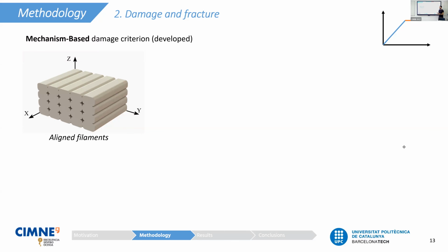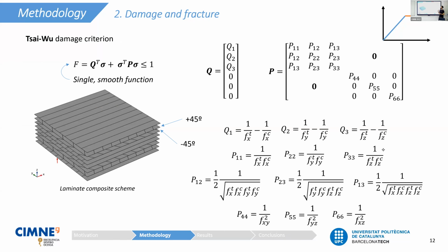However, the previous, let me go back 1 second. This Tsai-Wu damage criterion has one drawback, and that is it's a single smooth function, meaning it is just one scalar, and with just one scalar it is impossible to fully characterize all the different failure modes that are present in such a complex system. Because in the end, the different printing patterns present in a FFF component have more than one failure mode, and one single parameter cannot capture all the physical singularities that appear there.